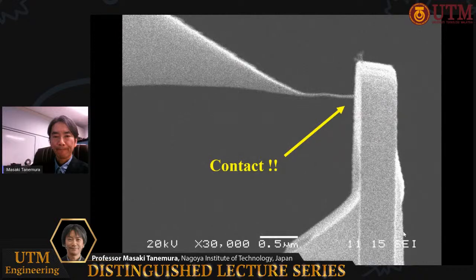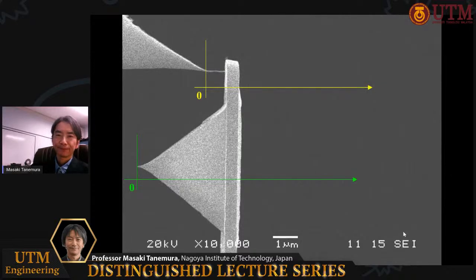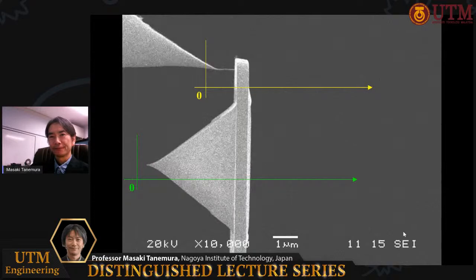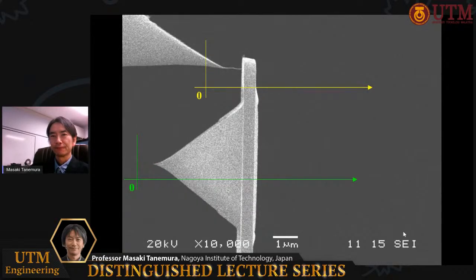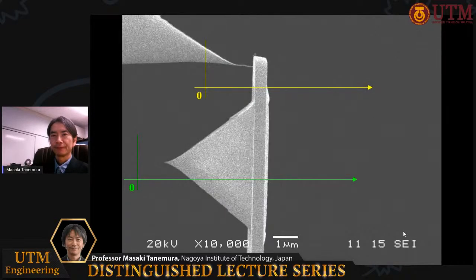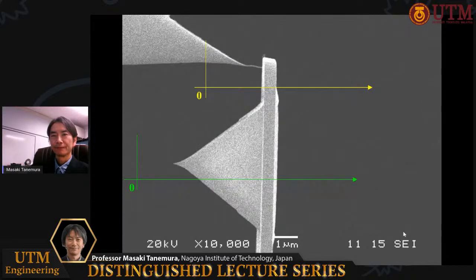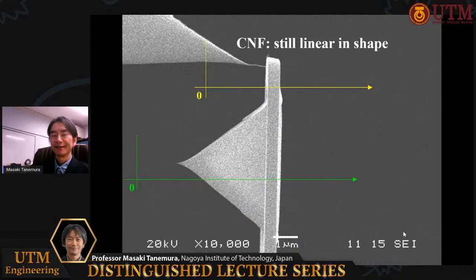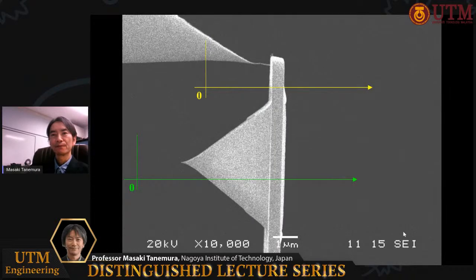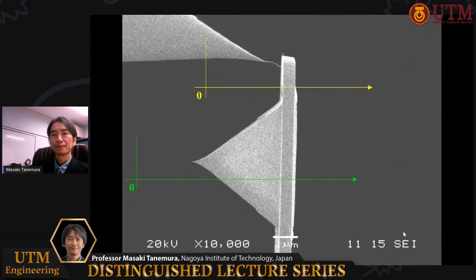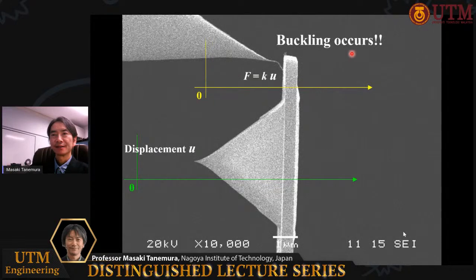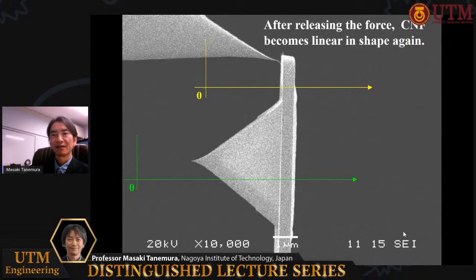We will start the measurement. The carbon nanofiber is still linear in shape. Here, buckling occurs. From this displacement U, we can calculate the force acting on the carbon nanofiber by the equation F equals KU. We release the force, and the carbon nanofiber becomes linear in shape again, like the initial shape.